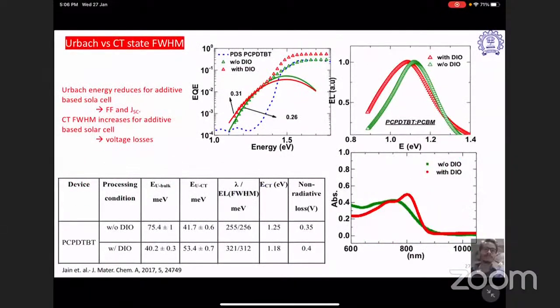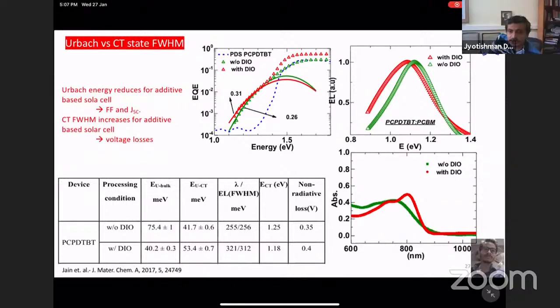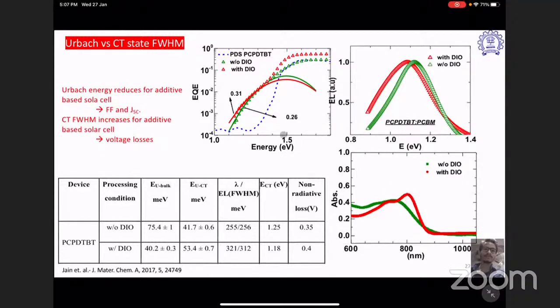And that was clearly seen, a clear-cut change in the Urbach energy. So there is with DIO and without DIO. Without DIO, you have a very slanted absorption, whereas with DIO, you get a very steep one. And that is a very clear-cut signature, from the inorganic semiconductor knowledge, that things are getting much more ordered in the system. Dinesh, could you use the cursor? We couldn't see which data you meant. Okay. Is that okay? So this is the change in the Urbach energy with and without DIO.